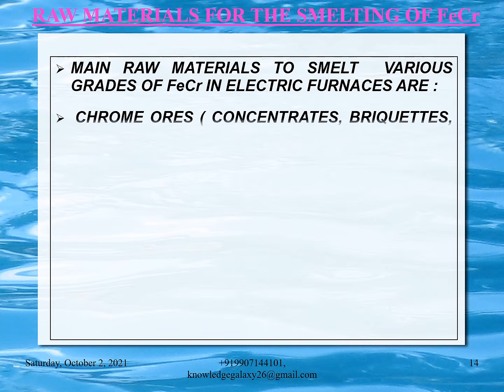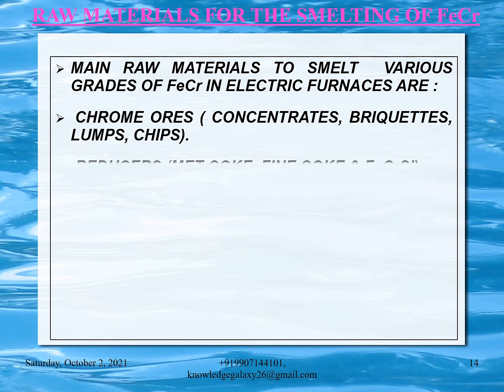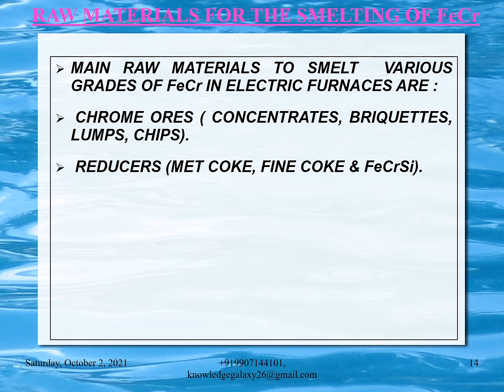Now let us discuss the raw materials required for the smelting of ferrochrome. Main raw materials to smelt various grades of ferrochrome in electric furnaces are: first, chrome ores, that is concentrates, briquettes, lumps and chips. Second, reducers, met coke, fine coke and ferrochrome silicon. Third, fluxes, quartzite and lime.